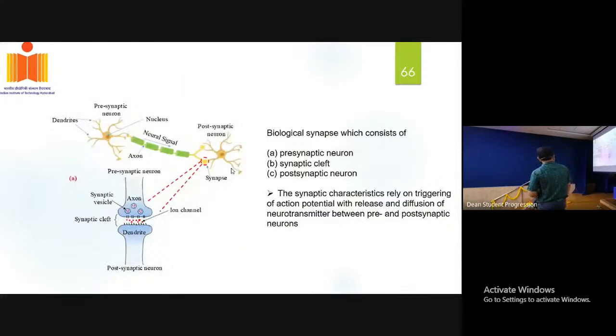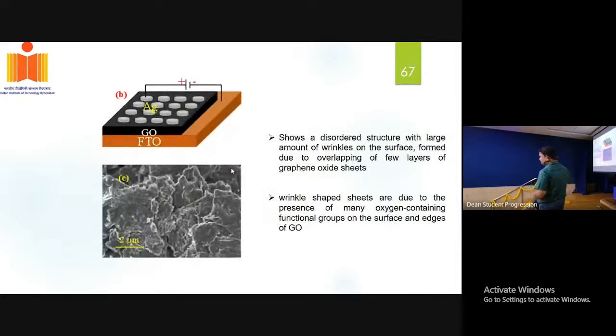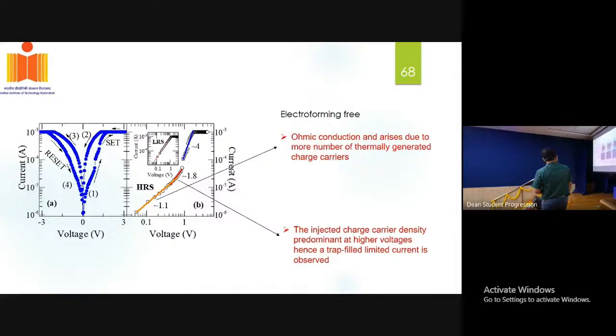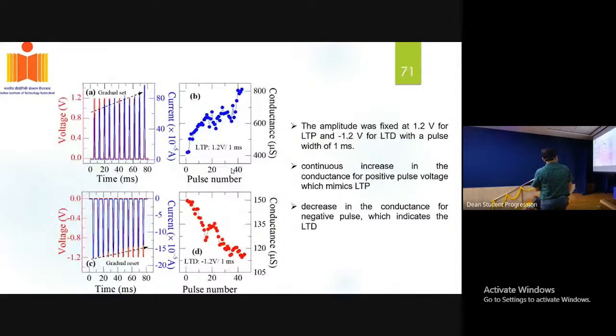So for this purpose, we tried to develop a device based upon graphene oxide to mimic brain functionality. When we apply positive voltage pulses, we see an enhancement in the conductance. When we apply negative pulses, we see a decrease in the conductance. That means the device is exhibiting long-term potentiation, and here the device is exhibiting long-term depression.